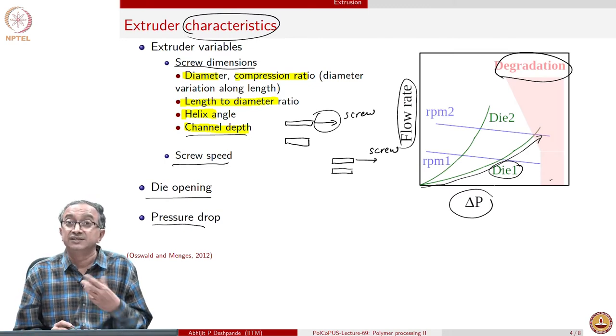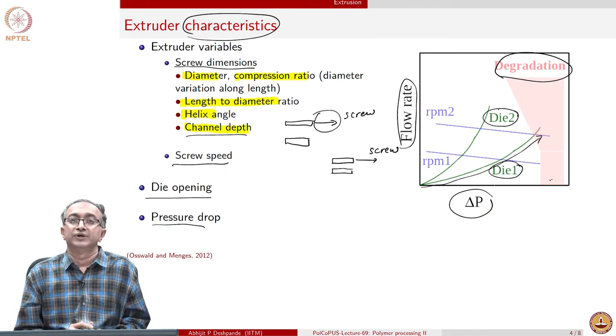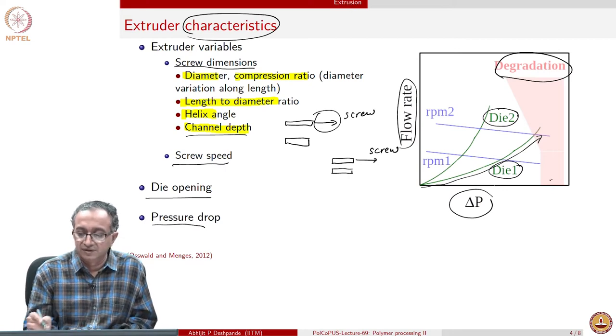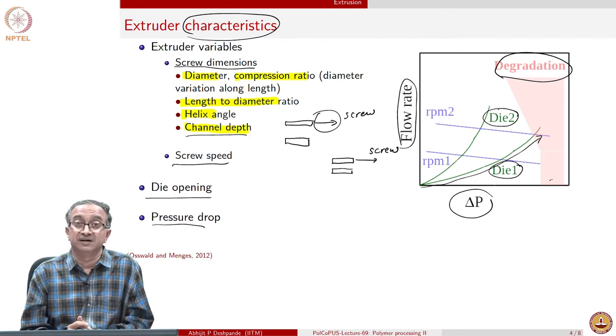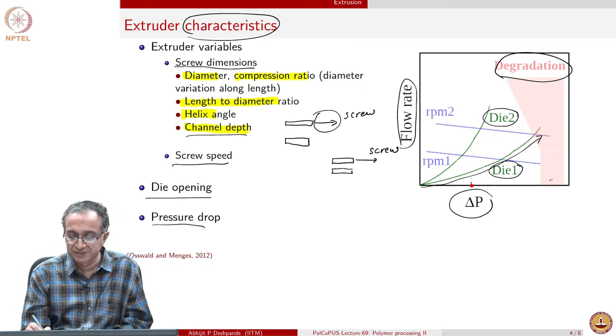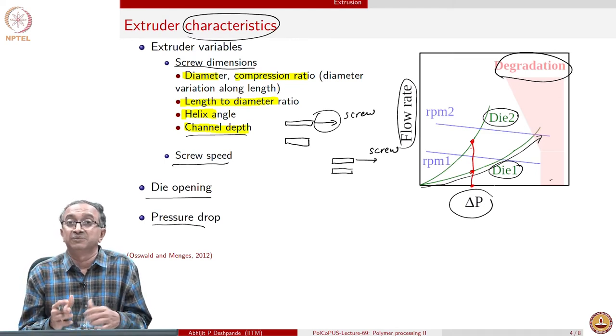When you change the die size, you will get a different flow rate versus pressure drop characteristic. Looking at this graph, can you make out which diameter of die is higher? Is die 2 diameter high or die 1 diameter high? To think of it, you can just pose this question: at the same pressure drop, which one gives me higher flow rate and which one gives me lower flow rate, and why? So I'm sure you can quickly see that die 2 ought to have a bigger opening because I get much more